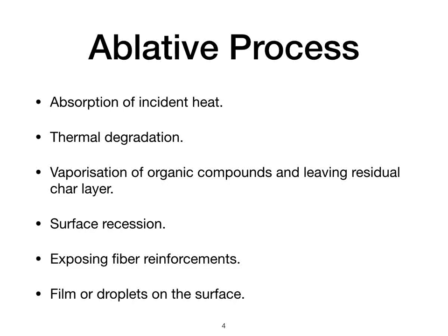Thermochemical and mechanical attack of this porous carbonaceous structure results in surface recession, thus exposing the reinforcing fibers to the hot gas stream. Fusion of the fibers occurs and the molten material covers the surface either as a film or as droplets. This melt is partially vaporized and the remainder is convected along the surface under the influence of the external forces of gas pressure and shear.